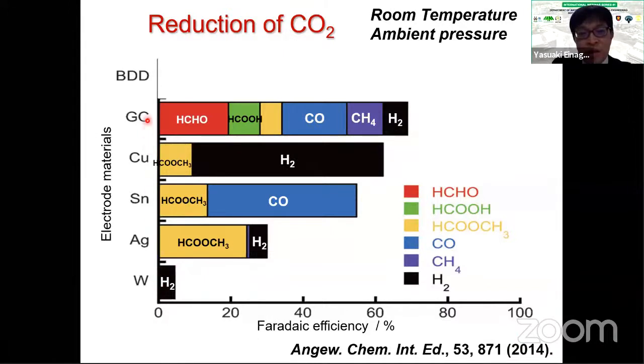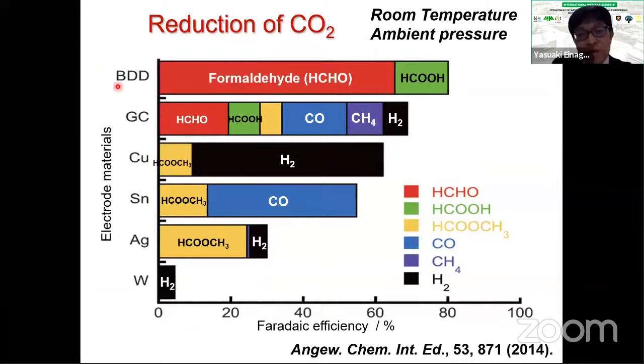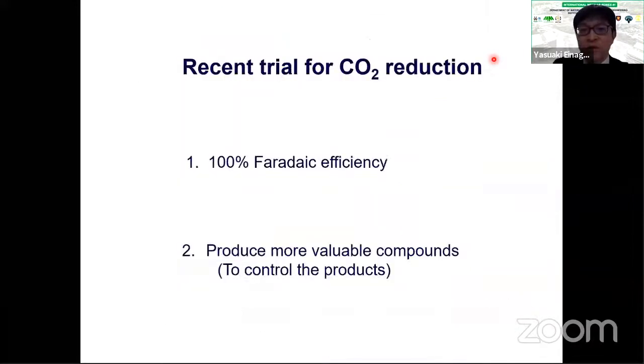As you can see, this is a conventional electrode, and surprisingly, when we use boron-doped diamond, formaldehyde was produced with very high efficiency at room temperature and ambient pressure. This was very surprising data for us. After that, many people became interested in CO2 reduction using the diamond electrode, and now we are also focusing on this topic.